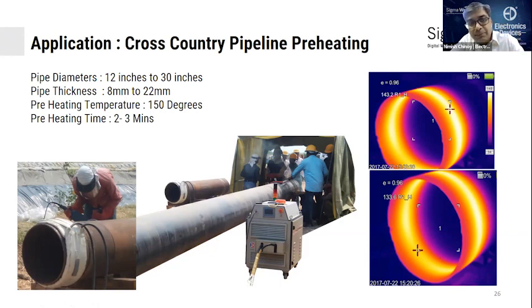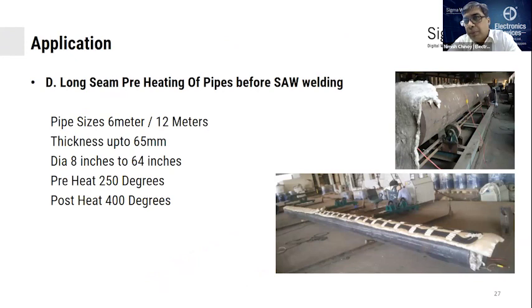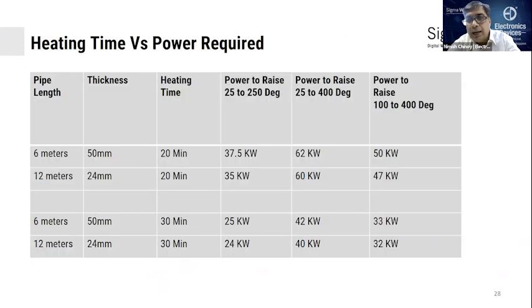And to apply this blanket, it takes about 2 minutes. Heating time is about a minute or 2. In 5 minutes, the pipe is ready to be welded. They have to weld kilometers of this together on cross-country pipelines. Induction heating provides a very fast and consistent service. If you look at long seam pipes being welded, again the same application, preheating for a 65 thick pipe, we could do it within 20 minutes. And these are the calculations for the same.